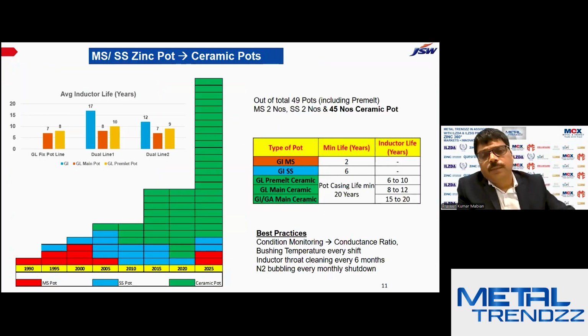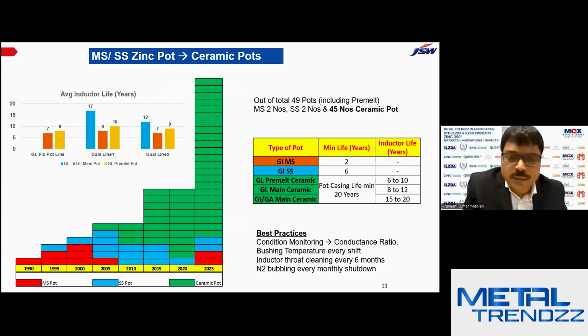This is about the metal pots, the zinc pots, which were used in the metal coating lines. Initially, you can see all the red color, which is steel pots, MS pots. We call them Armco steel pots. Later, you can see blue, which is stainless steel pots. JSW was the first company in India to start with the stainless steel pot, SS316L pot. Right now, we have almost all ceramic pots. Out of 49, we have 45 ceramic pots, 2 MS pots and 2 stainless steel pots.